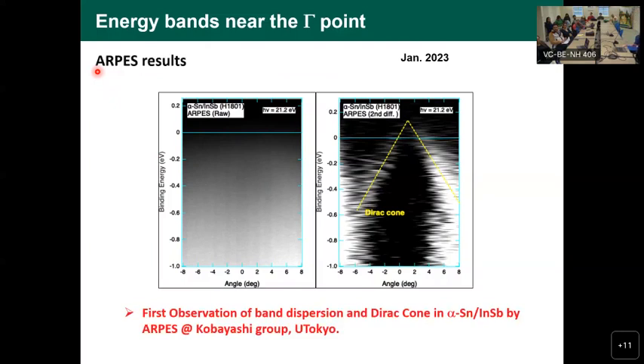And here we show, this is very rough data, but it's the ARPES results. Guys, I think you know about Dirac, okay? You know about Dirac, and we have what we call the Dirac cone. Sometimes the electronic structure shows a cone. So there is an intersection in the bands, and this point, we're looking for this point. And there are some exotic states like Majorana fermions and so on. So we could roughly observe the Dirac cone in these preliminary measurements. I hope also to proceed with this.